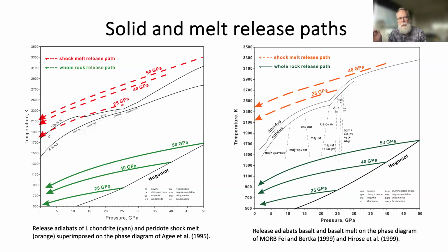You can melt material on decompression. Definitely if you're crossing the melting curve on decompression, you can melt. Again, many people seem to think that the shocked material is hotter after release than at pressure, and it's not. It cools during release. It is much hotter after release than it was initially, though. But here's the thing, this gives us boundary conditions for interpreting the quench path of our shock veins. Here's just an example for a basaltic composition, so we can use this to interpret Martian meteorites, and you get very similar results, right?